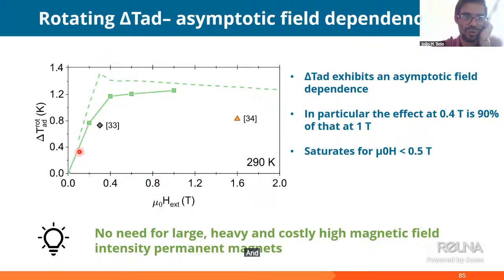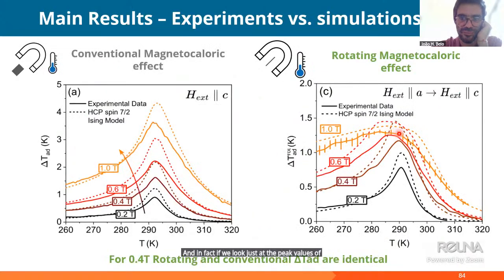And in fact, if we look just at the peak values of the delta T as a function of the external field intensity upon rotation, we see that this effect saturates. So it's really irrelevant to have a very large field because you are not going to have a larger delta T with a larger field. So this effect saturates at 0.5 Tesla for a gadolinium plate. So this tells us that in a magnetic refrigerator relying on a rotating magnetocaloric effect, one does not need a large, heavy, or costly high field intensity permanent magnet.